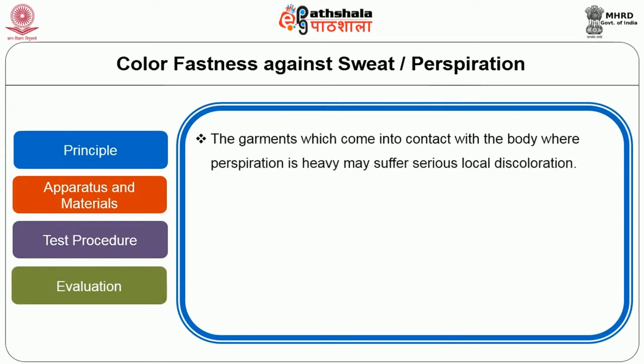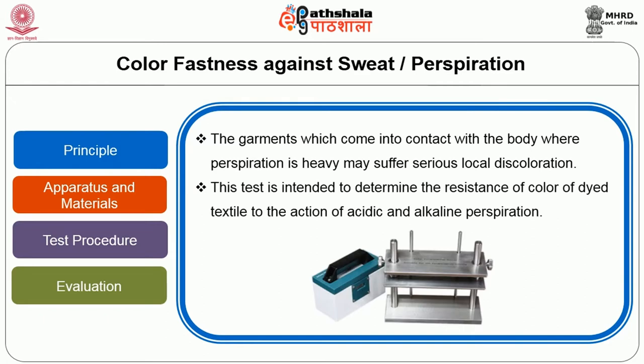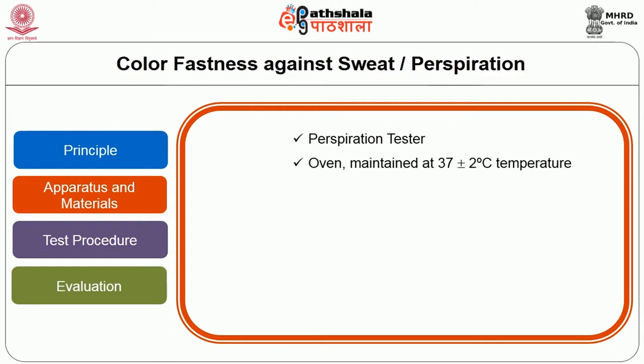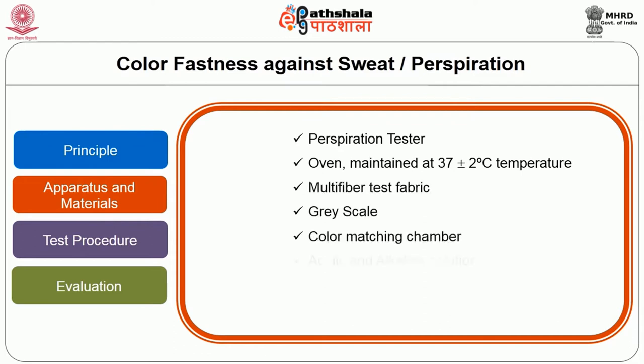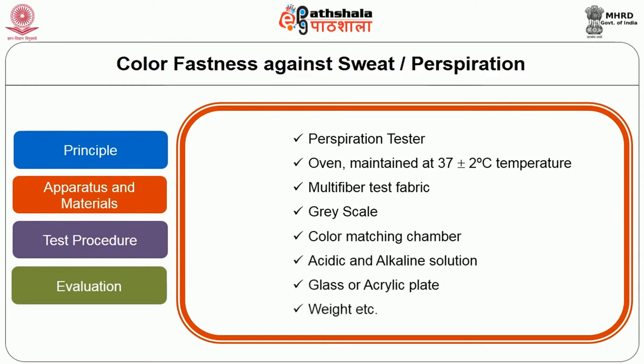Color fastness against sweat, also termed perspiration. Principle used: garments, mainly wovens, which come into contact with the body where perspiration is heavy may suffer serious local discoloration. This test is intended to determine the resistance of color of dyed woven textiles to the action of acidic and alkaline perspiration. Apparatus and materials: perspiration tester, oven that can be maintained at 37 plus or minus 2 degrees Celsius, test fabric, grayscale, color matching chamber, acidic and alkaline solution, glass plate or acrylic plate, weighing balance, etc.